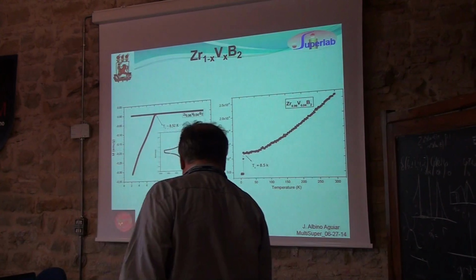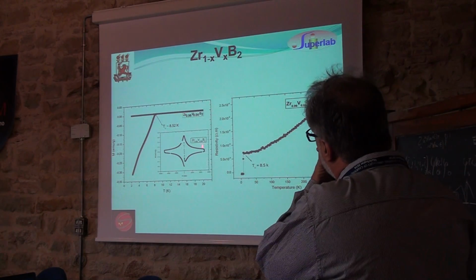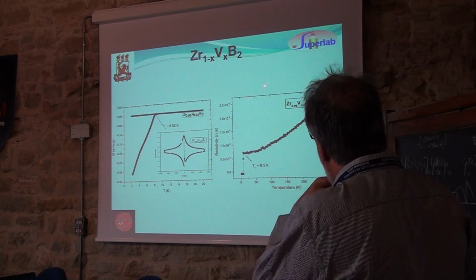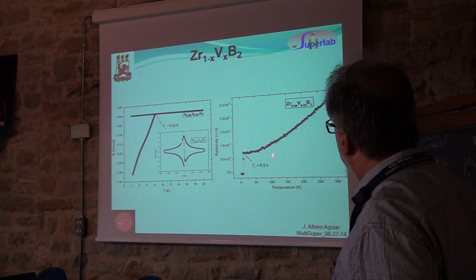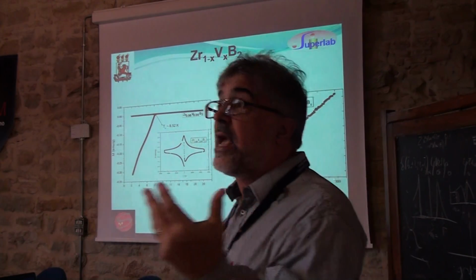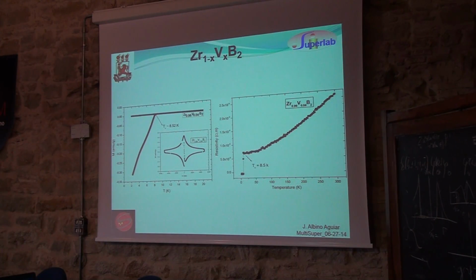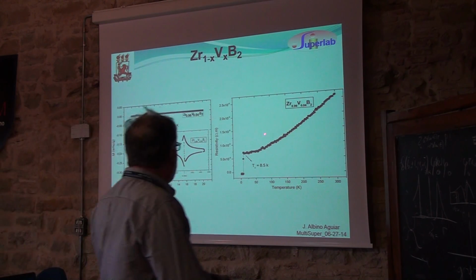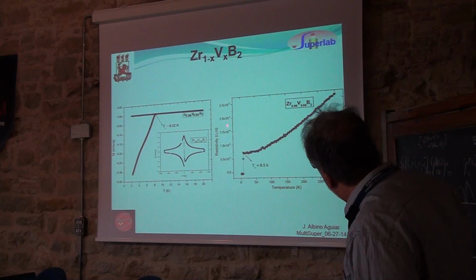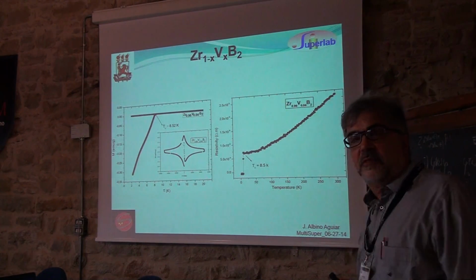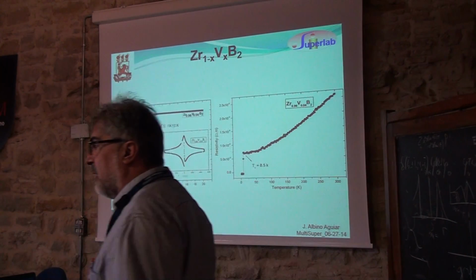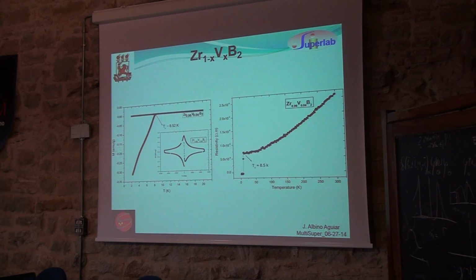So in this slide, I again reproduce the magnetic data. And here we have the resistivity data. You see also that it's a clear resistive transition. So we have no doubt that this is indeed a superconducting material. And I have to call your attention, look at these numbers. This is a very, very good metal. Resistivity here is 2.5 times 10 to the minus 8. Copper is 1.7 times 10 to the minus 8 at room temperature. This is a very, very good metal.